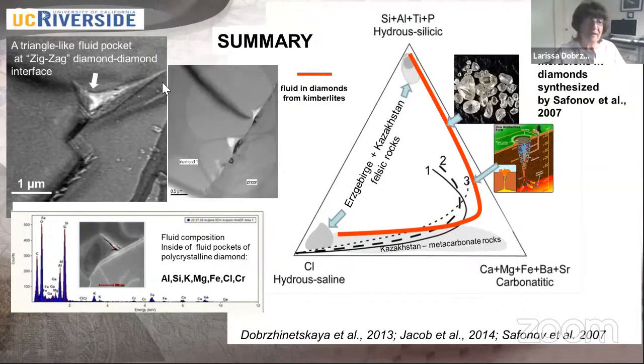So make a summary on that. Again, you see here fluid pockets. Here already perforated, but here fluid still alive. So we measured them and then combined all data. We plotted them on the triangle diagram of hydrous silicic, hydrous saline, and carbonatitic fluid, which was developed by scientists who study fluid in diamonds from kimberlite and in experiments. The curves 1, 2, 3 are experimental curves, which show the evolution of the fluid in experimental diamond, which was made from fluid in experiments. And the red line is the fluid evolution in diamonds from kimberlite.